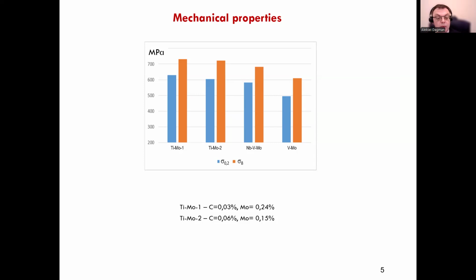steel with a minimum carbon content, maximum molybdenum content, and the end temperature of hot rolling and winding of 860 and 570 degrees centigrade respectively. At the same time, as the highest range values for the steels of this microalloying system, higher elongation values were obtained.